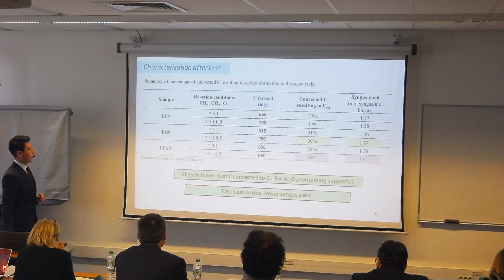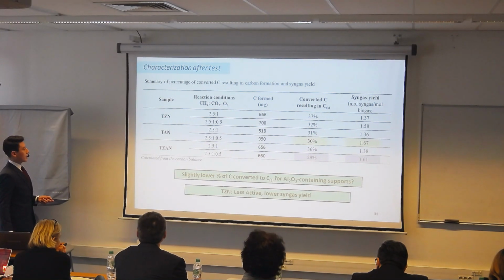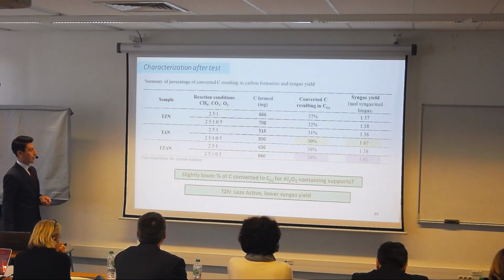Exactly as I mentioned before, as we have higher activity, we also have higher production of carbon deposition. The titania zirconia catalyst was the least active, with a lower syngas yield.